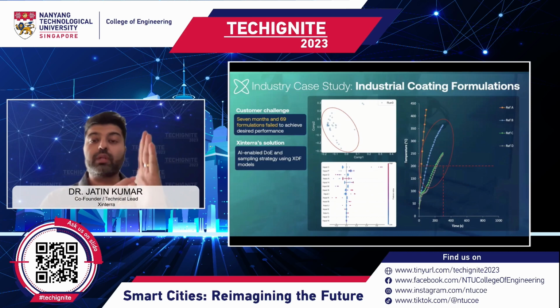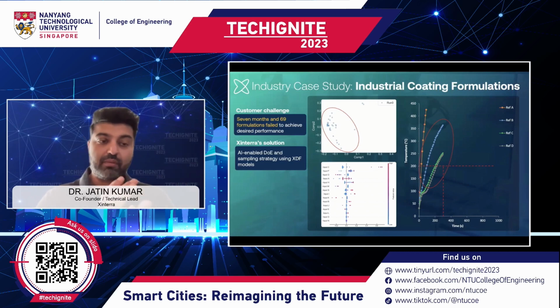And they subject that coating to a naked flame. Now, on the opposite side, they're measuring temperature. And the target that they're trying to hit is over 4 hours, the temperature on the opposite side cannot exceed 200 degrees Celsius. And so they've been trying for about 7 months. They tried about 69 different formulations. And what they found was that they weren't even close to achieving the target of 200 degrees Celsius.